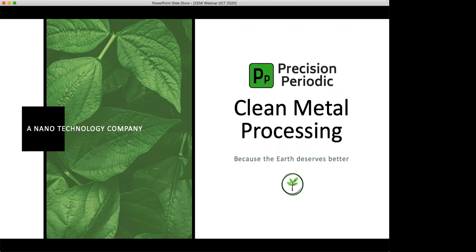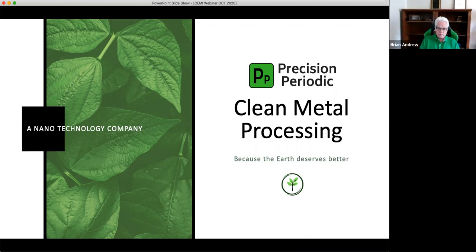Yes. 75 microns or smaller is fine, up to 12% we've actually done, but the gap in the beads is quite large. These beads are about two millimeters in size, and we run a long, relatively tall, not too wide a column, so you've got plenty of time for the water to touch the beads as they go through. And so suspended solids are not a big issue with this. And we aren't upset by extremely high concentrations of other materials, like literally 100,000, 200,000 parts per million salt doesn't upset 0.1 part per million gold extraction. That's fine. The specificity of the filter, we can tell it to get 0.3 parts per million gold, actually one part per billion, in a liquor that is basically rusty water or salty water or both.